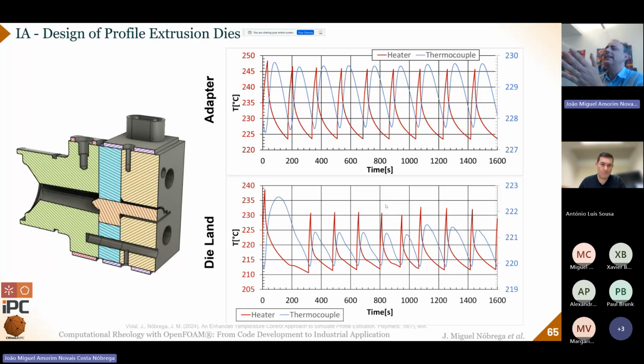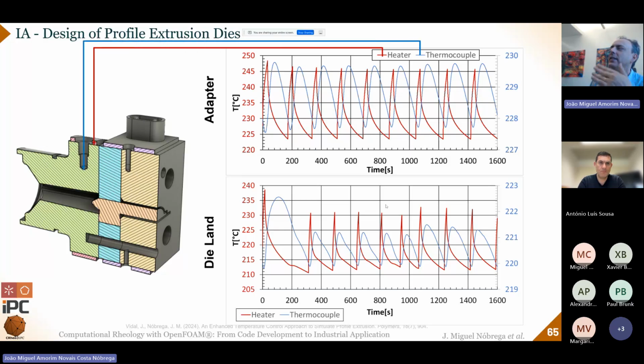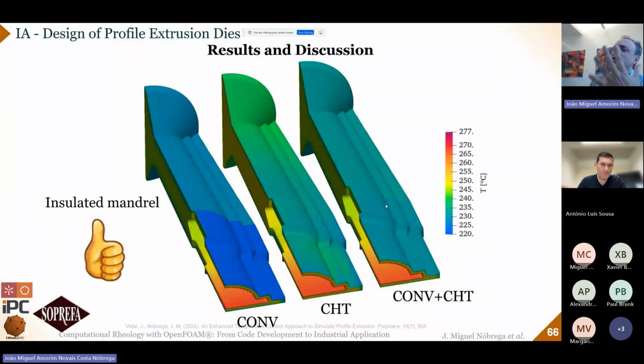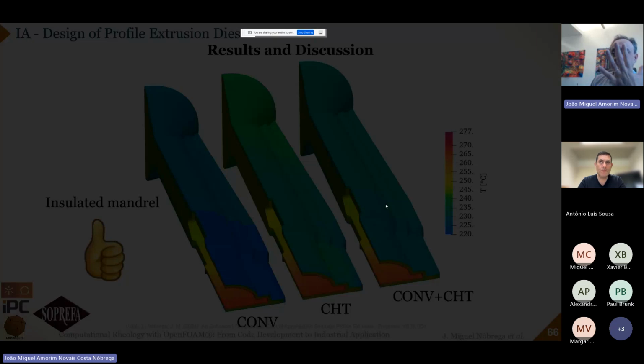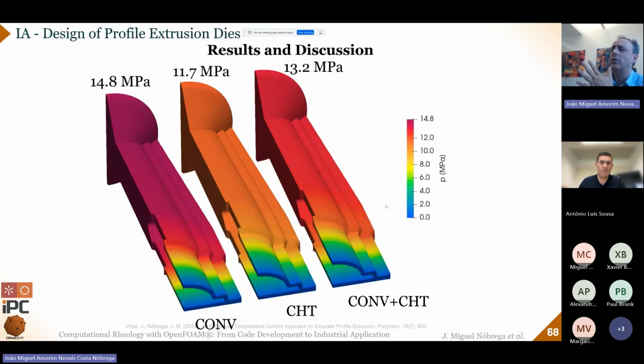Again, here is the unsteadiness of the process that is illustrated, where we have the reading from the thermocouple, in this case a virtual reading, and the activation or deactivation of the heater, and the process becomes quasi steady state, but it's not steady state because there are oscillations motivated by temperature, and we figure out that there are some options that are appropriate, but there are other measurements we get that are not so accurate.